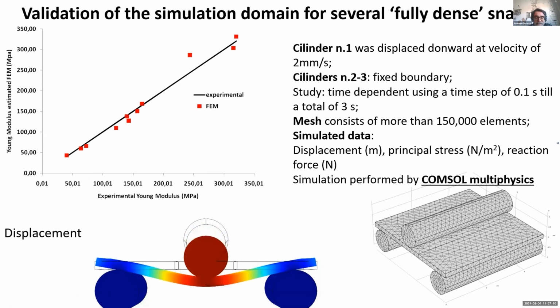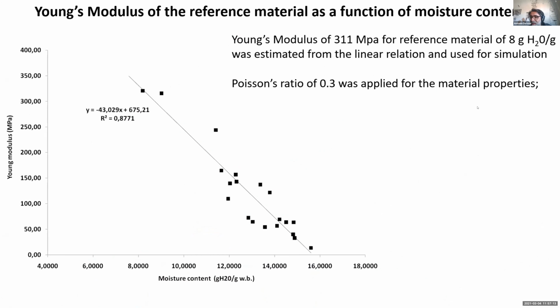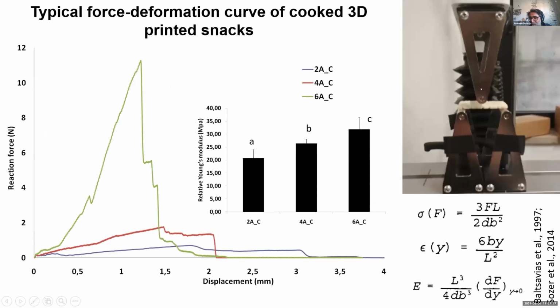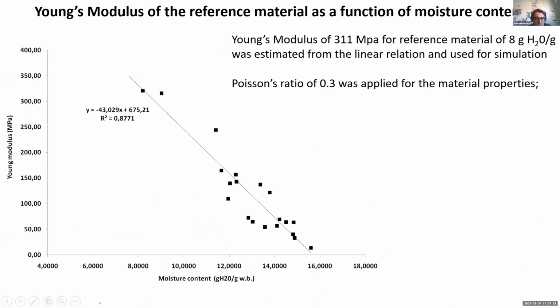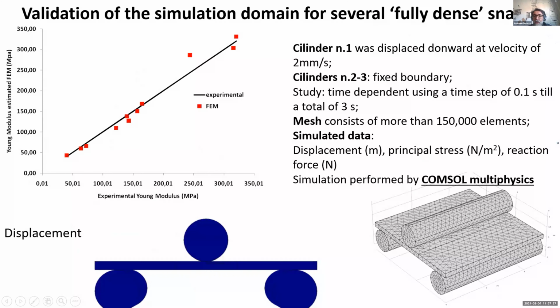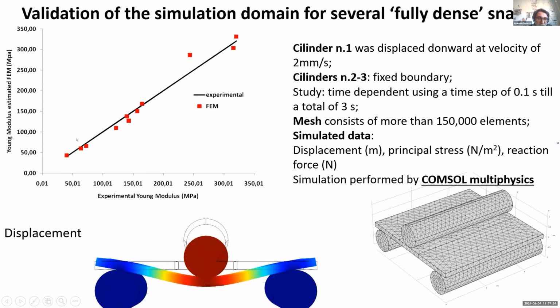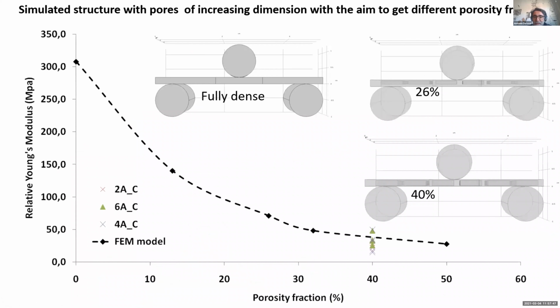And then we modeled this with our FEM methods. It is the same application that we can see here. We have two different cylinders, and this cylinder moves before the snack breaks. We model it in the same way, at the same velocity as the experimental test. This is the validation: the black line is the experimental value, and the other is the value estimated by COMSOL. And then, the last step was, if we introduce in our model, this is the fully dense, 26%, the 40%.